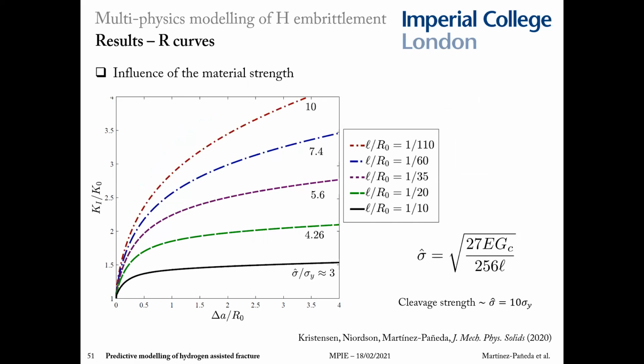And here you can see how the crack growth resistance changes with the material strength. And this is important to showcase how our model can naturally capture the shift from ductile to brittle fracture once hydrogen comes into the picture. Because for each value of the strength, you can compute a steady state fracture toughness where the R curve becomes flat, so this region here. And we know that brittle interfaces such as grain boundaries have a strength on the order of the theoretical lattice strength, so 10 times larger than the yield stress approximately.